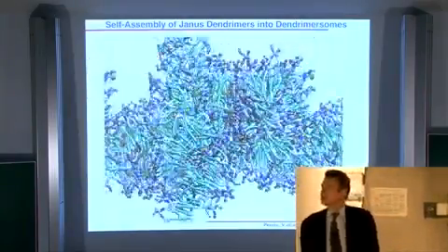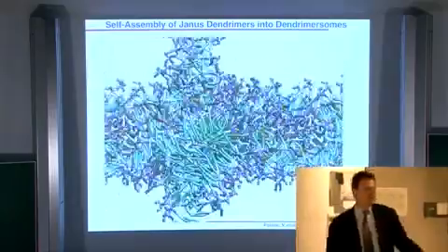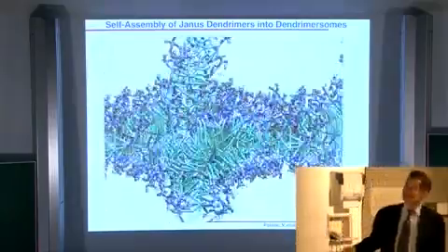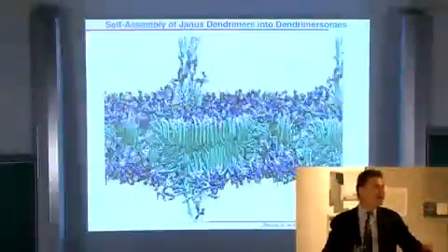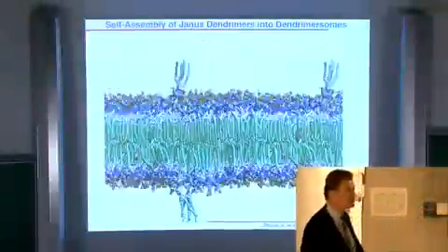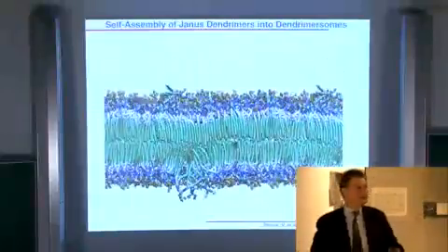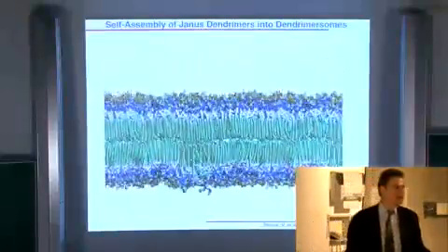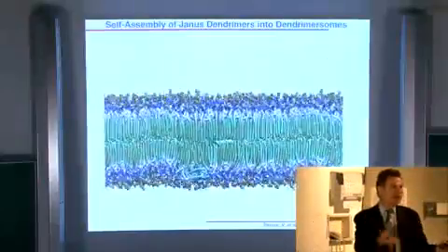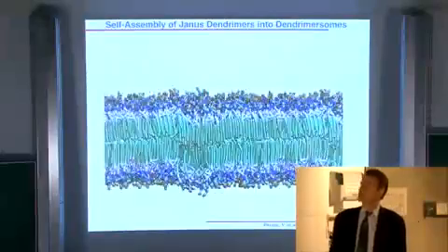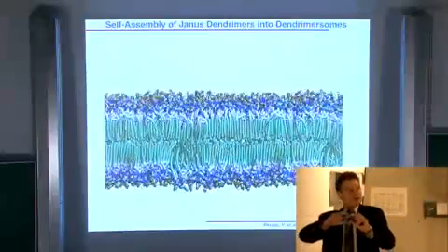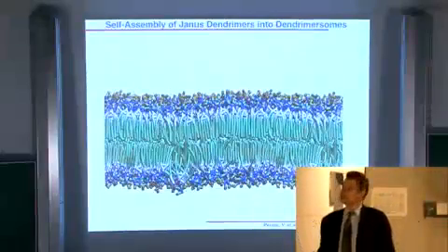This is how the molecules come together, and you see the complexity in part of the structure. The conformation of the assembly doesn't have anything to do with the conformation of the individual molecule. The molecules first get hydrated with water, and the hydrated molecule is different from the non-hydrated molecule, and ultimately they make a bilayer, but this bilayer is only a fragment of the vesicle.